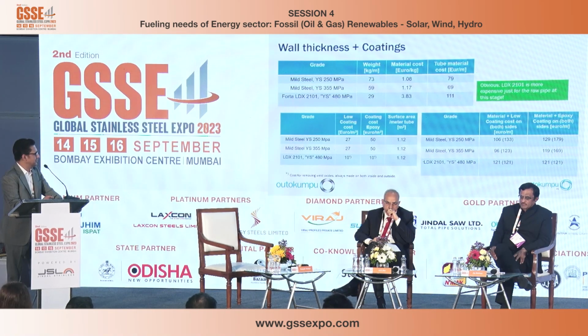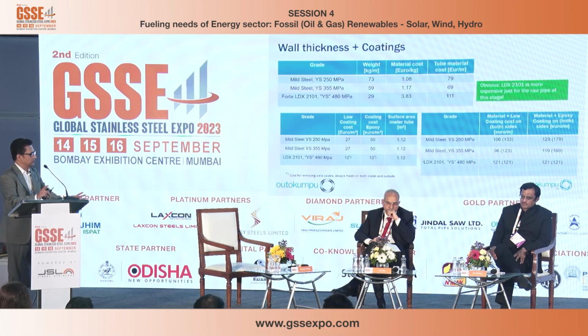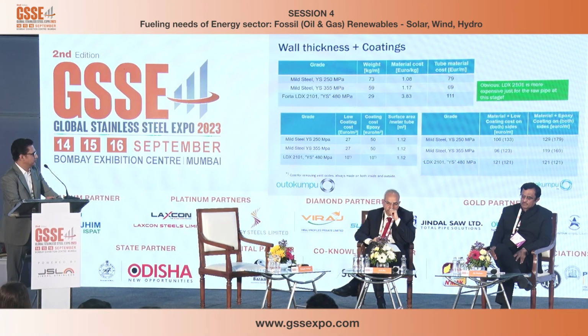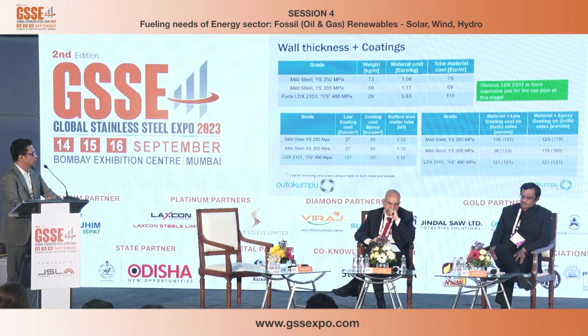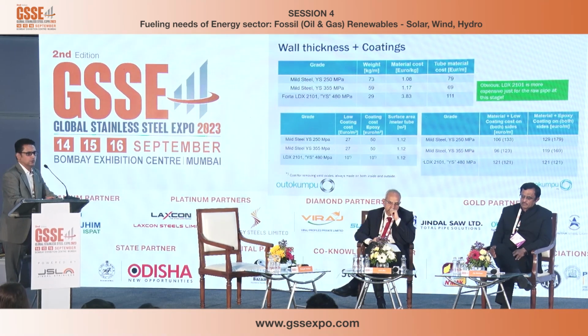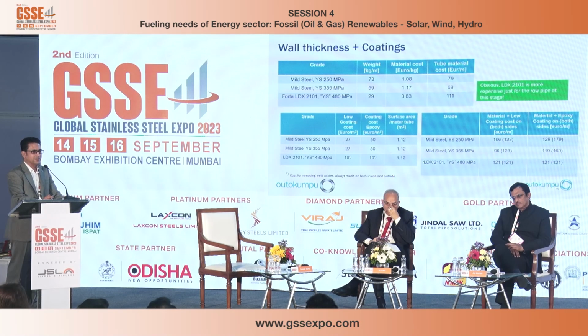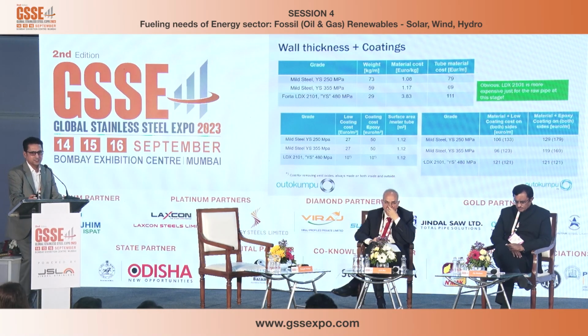On the right side table, if you see, when you put these figures, in mild steel material when you are using the low cost coating, whether on one side or on both sides, depending upon the application, for mild steel it is 106, 133, whereas with epoxy coating 129 and 179. Similarly, when you go to the duplex stainless steel, it is 121, whether you do one side or both sides. So in comparison, duplex in the initial stage itself is working out to be cheaper than the carbon steel.